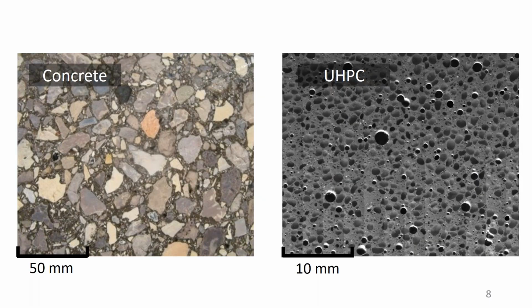This slide kind of shows the difference between them if you were to slice a piece of concrete and UHPC. Notice that the one on the right is 5 times magnified over the one on the left, so you can see some of the features. You're all familiar with concrete, but with the UHPC, you notice the uniformity of the surface. That is the key difference between them. There's really no big aggregate in the UHPC.